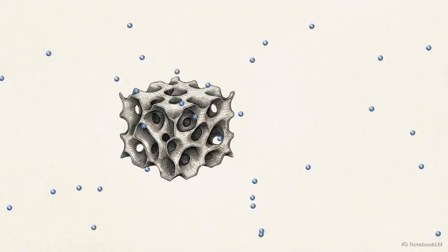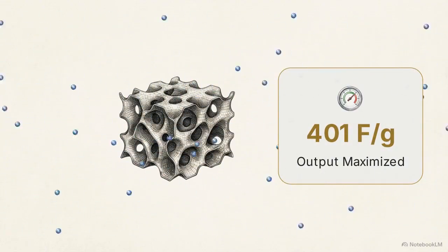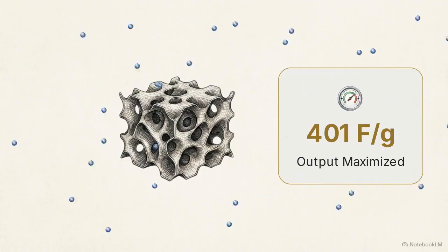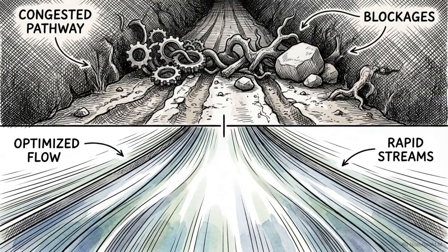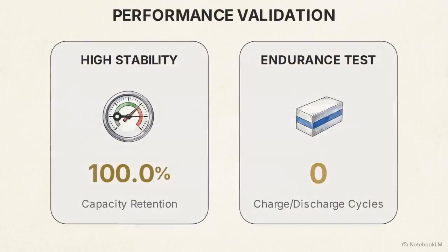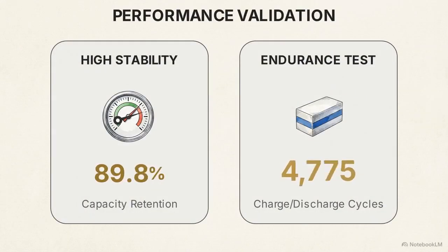This forms a porous 3D network, increasing surface area for ion transport, pushing output to 401 farads per gram. The hydrothermal process physically upgrades the material from a restrictive, slow pathway into a high-capacity superhighway, capable of retaining 89.8% of its charge over 4,775 cycles.